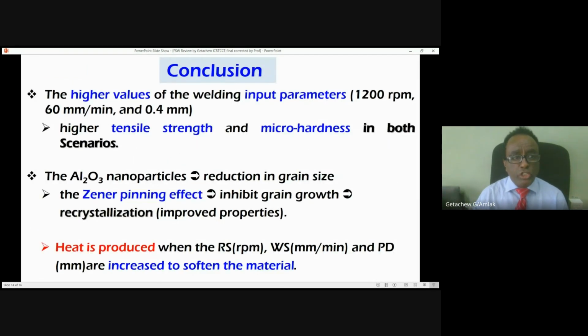When you come to the conclusion, in both scenarios the combination of the process parameters was the same. The rotational speed was 1200 revolutions per minute, 60 millimeters per minute of welding speed, and 0.4 millimeter of tool plunge depth, especially from the shoulder point of view. Due to this, higher strength has been achieved and higher micro hardness is disclosed in the results as compared with the previous or traditional one.